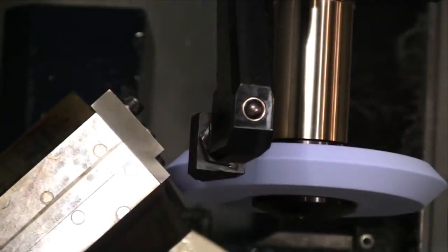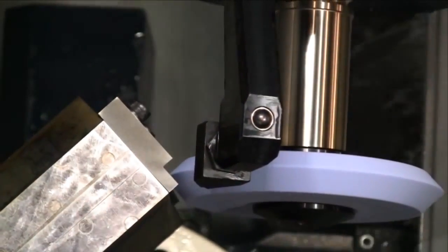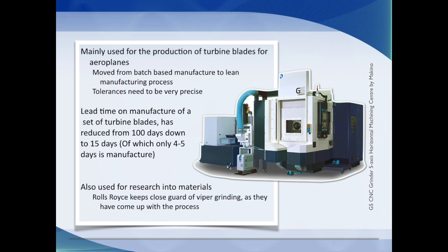High-speed grinding is effectively where you use Viper and add it to the continuous dress process. With high-speed grinding, manufacturers are able to achieve metal removal rates of 16 cubic inches per minute in grinding alone. Obviously, there are still limitations to grinding. With the development of high-speed grinding and Viper, it's no longer the material removal rate, and now it's more the wheel access.